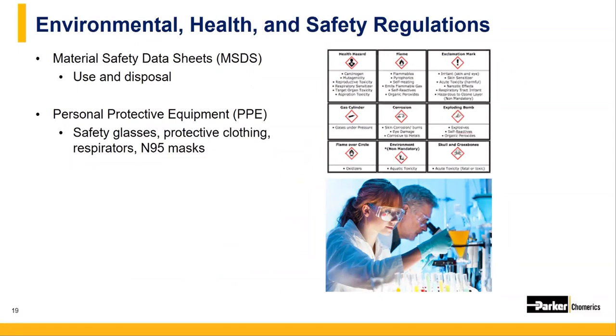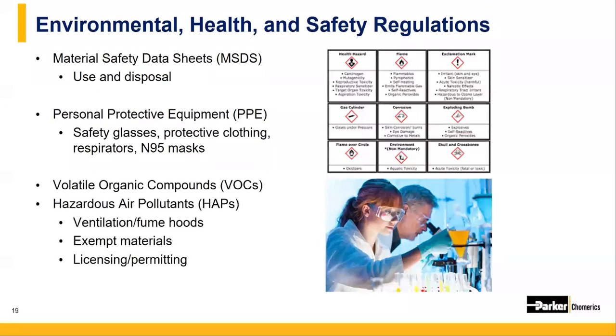Proper PPE should always be used, and because nearly all coatings are solvent-based, they should only be sprayed in well-ventilated areas and under a fume hood. VOCs, or volatile organic compounds, as well as hazardous air pollutants, or HAPs, are the gases emitted when spraying coatings and are contained in different amounts in each type of coating. Some solvents are actually considered exempt materials by the EPA and therefore are not included in the VOC calculation. In this case, these exempt materials can be used to formulate coatings with lower VOC content to meet company environmental requirements. Examples of these exempt materials can include acetone or PCBTF.